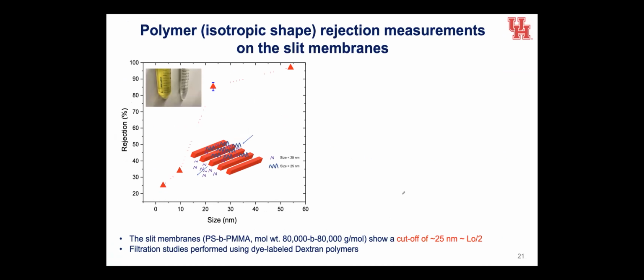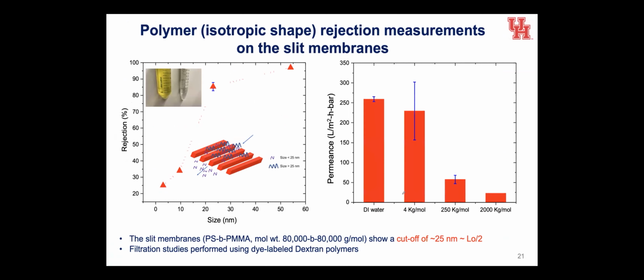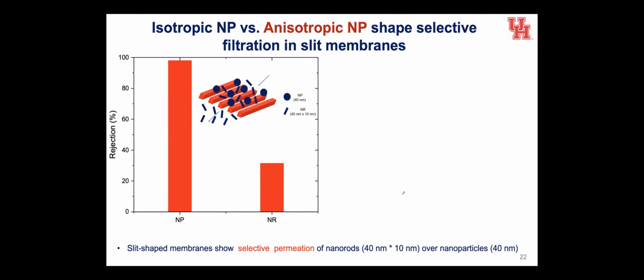So nanoparticle rejection, we do a lot, and we're able to show that a circular particle versus a rod-like particle can be separated in lamellar block polymers because the rods can align with the slit and go through. And we have GISAXS as well to confirm these as they go through. But what we really like to do is have in situ operation of these membranes and do GISAXS as it's separating. So then we'd be sensitive to what is going through the location and so on. But that's the next horizon of GISAXS.